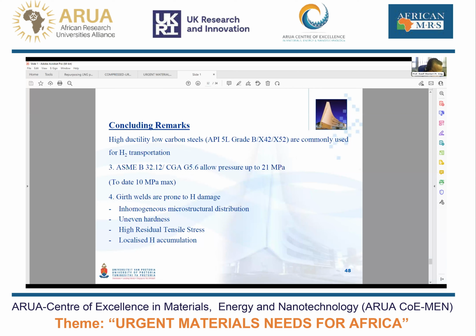So concluding remarks, I think I'm largely within my 20 minutes. Yeah, the concluding remarks are that what we found in our investigations is that high ductility carbon steels with slightly elevated strength, X42, X52 grades, are commonly used for hydrogen transportation pipelines. So typically a maximum pressure of 21 megapascal is allowed by a particular design code. The existing pipelines run up to 10 megapascal internal pressure maximum.